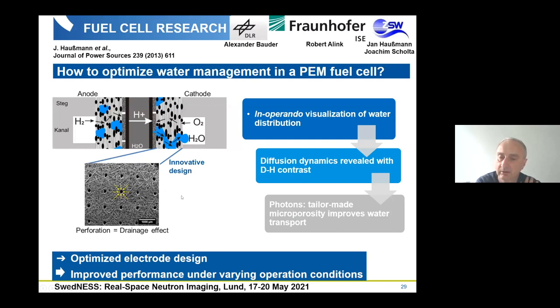Therefore, there was an idea from some industrial partner to make a good organization of the gas diffusion layer here, where we have two flows. On one side, we have water flow through the porous media in order to get the water out, away from the area of reaction. And the other flow is just the gas flow of oxygen, which we need for the reaction. So we can try this kind of geometry, some drainage, where if we use some hydrophobic material for the porous structure, then the water will be forced to follow the channels. And then we have free area for the gas flow for the reaction. So this was just a try to organize a bit better the flows in this gas diffusion layer.